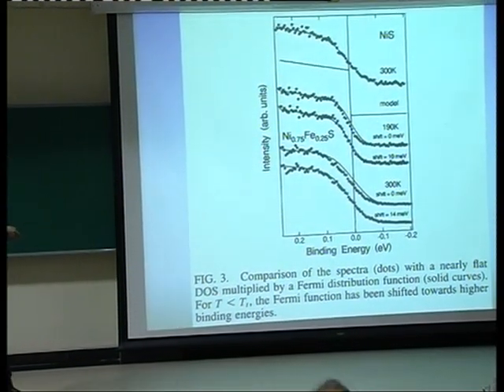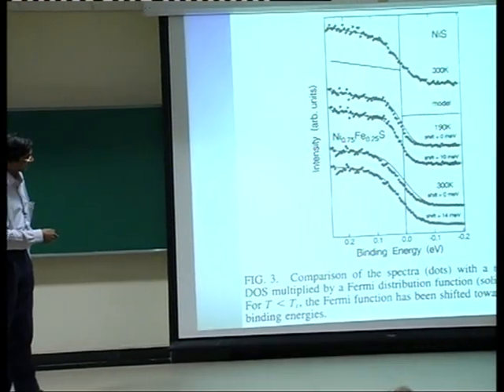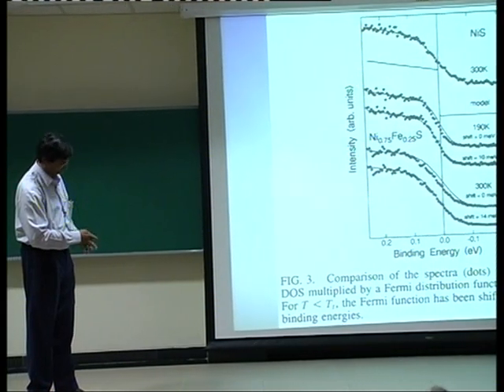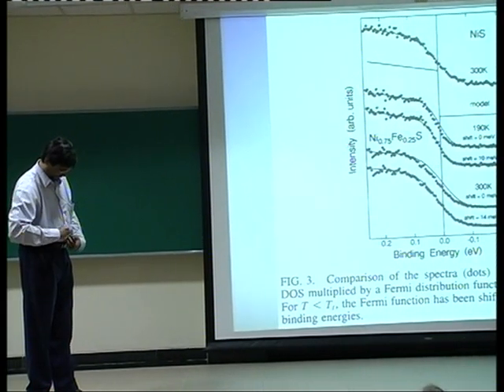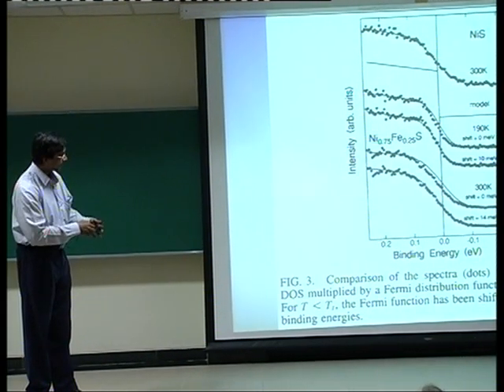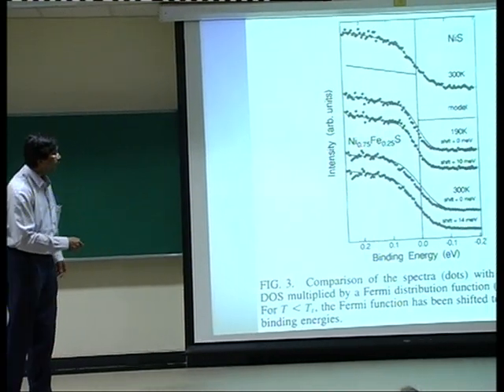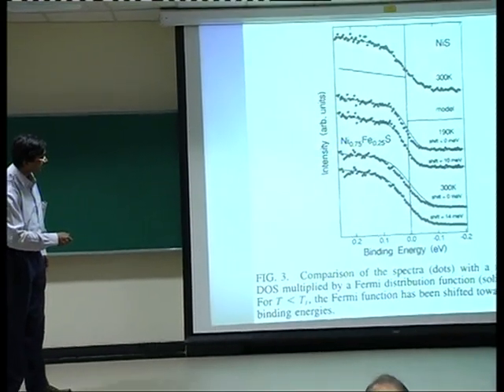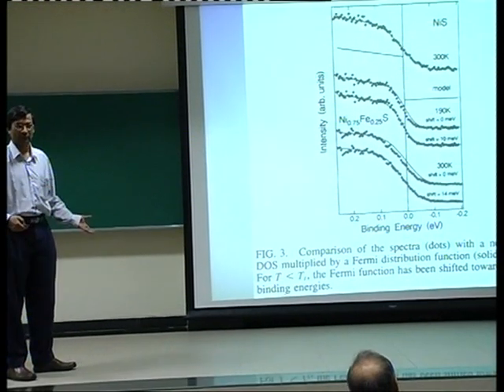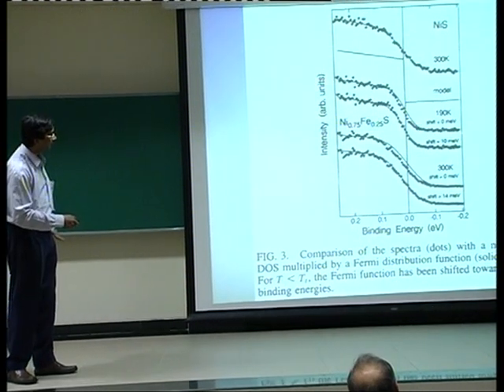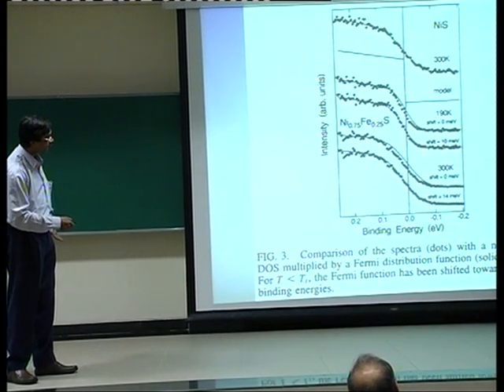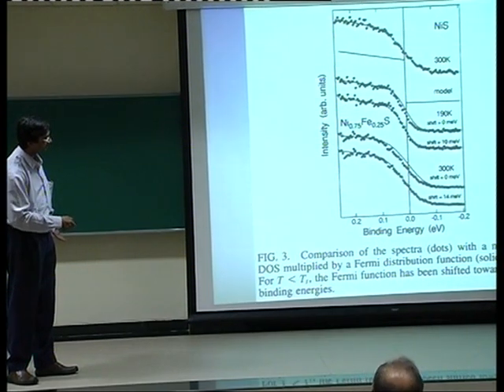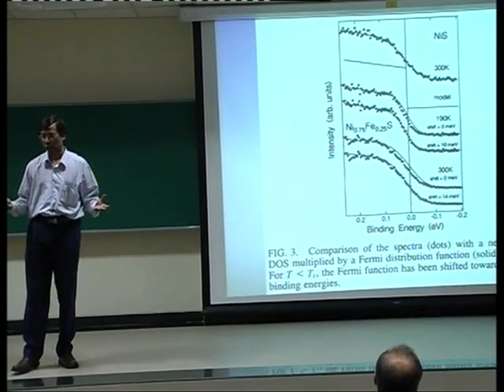And that, in order to estimate exactly how much that gap is, what they did was to shift this solid line rigidly to the left by a certain amount. Okay, and then they shifted it by 10 millivolt, and you see how beautifully it then describes. And they came to the conclusion, so it has a 10 millivolt gap.